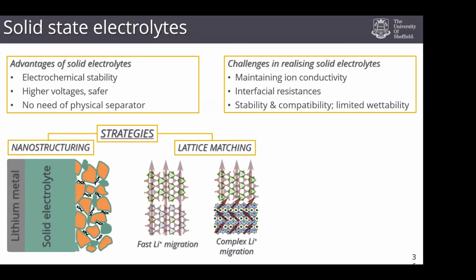We've been doing this in two different ways. We've been taking solid electrolytes and forming a tiny, thin, almost nanoscale coating on the surface of cathodes, to make that coating very intimate so that you've got very good surface coverage. The more interaction you have between the cathode and the solid electrolyte, the more chances you have of lithium ions being able to move between the two.